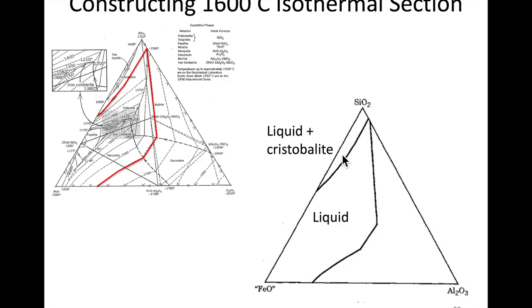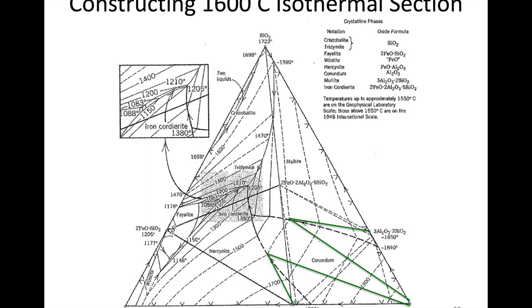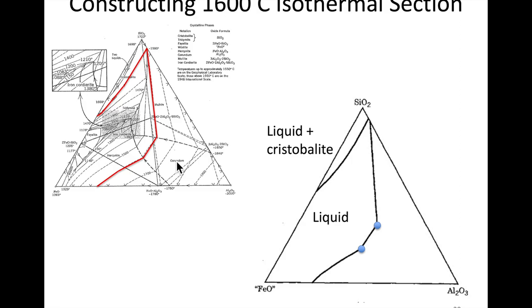For your reference, Christobalite is SiO₂ — basically the pure component of SiO₂. Now we can look at the other sections. There are two breaks and three separate lines. For this first portion, you'll see mullite; for this next part, you'll see corundum; and for this last part down here, you see hercynite. So that's going to tell us what phases we have in those three regions.